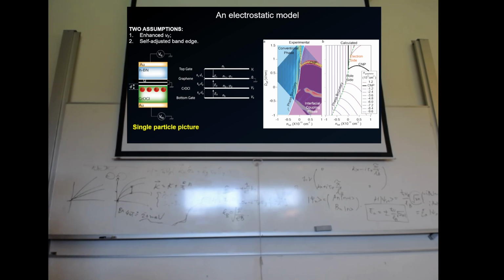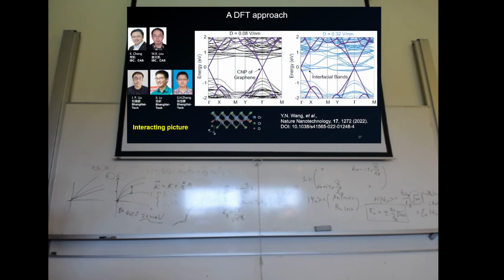That means even without any Coulomb interaction, using the very simple model, together with some assumptions, we will already reproduce the data to some large extent. That means this hypothesis might be correct, okay? So there should be indeed a kind of surface state in the material down there of graphene. So then we can do some DFT approaches using the hypothesis from the conventional classical model.